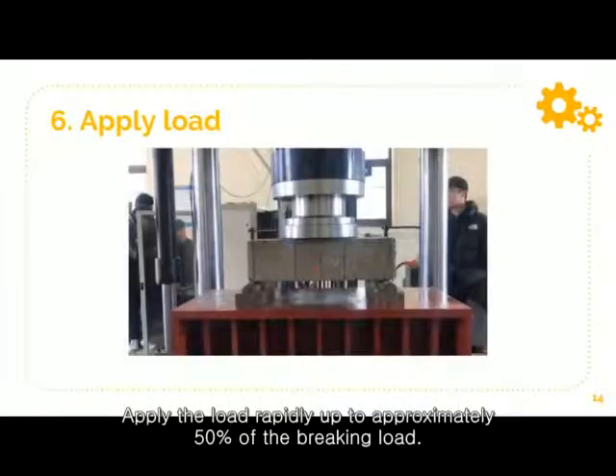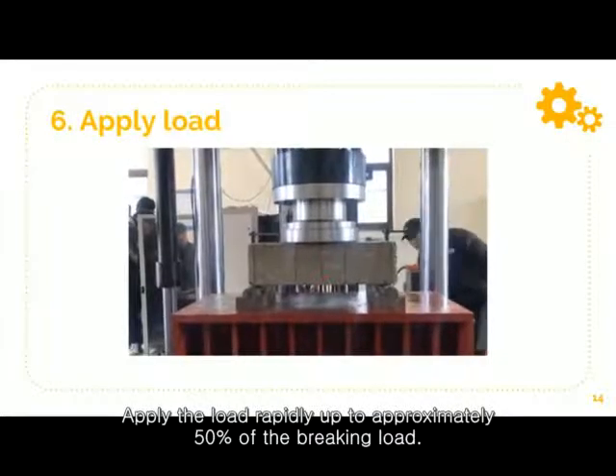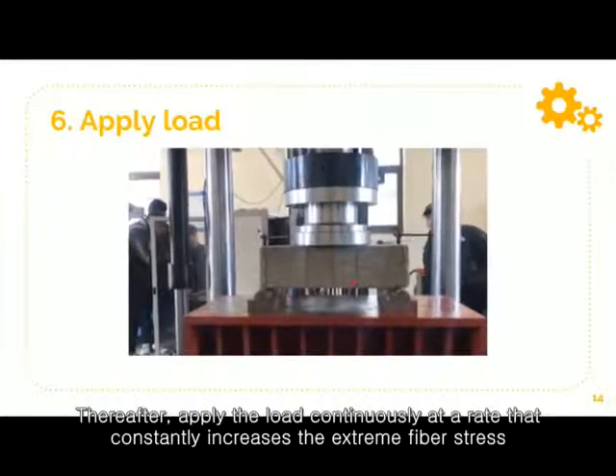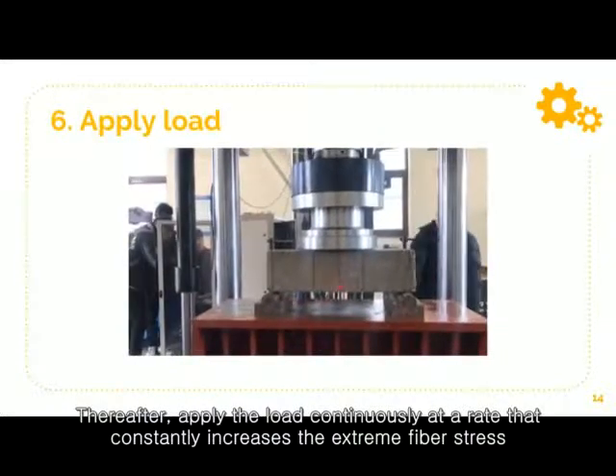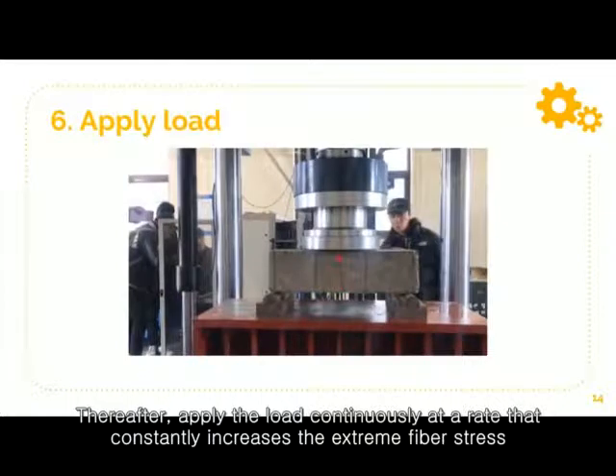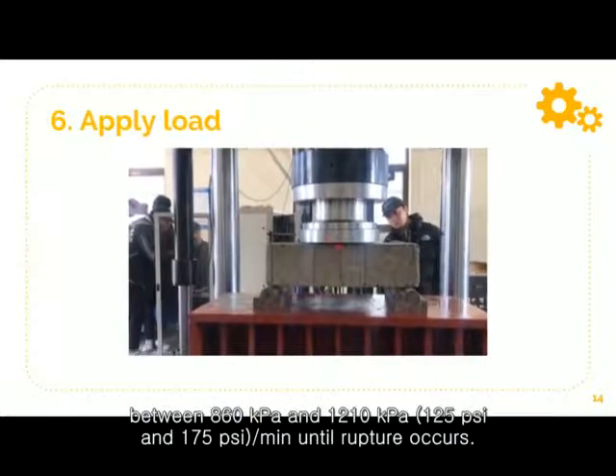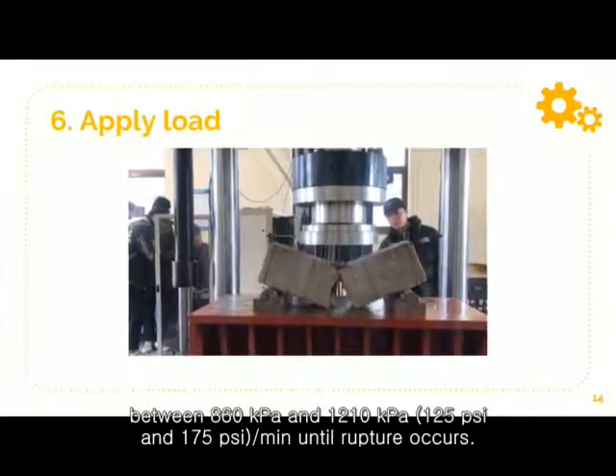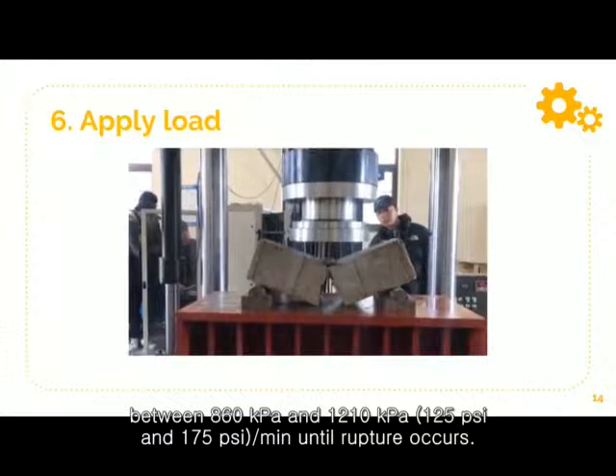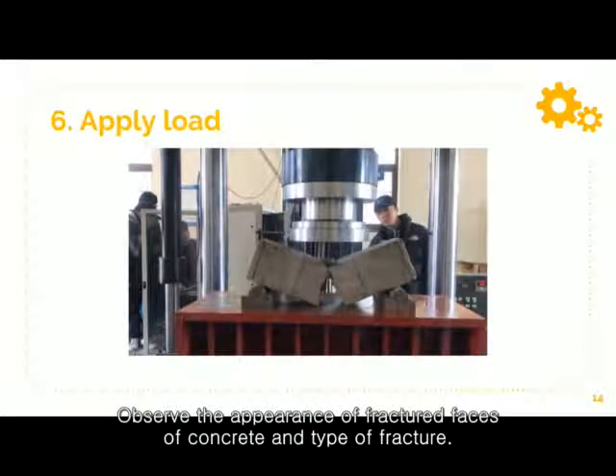Apply the load rapidly up to approximately 50% of the breaking load. Thereafter, apply the load continuously at a rate that constantly increases the extreme fiber stress between 860 kPa and 1210 kPa per minute until rupture occurs. Observe the appearance of fractured faces of concrete and type of fracture.